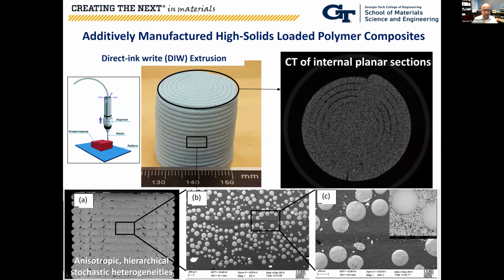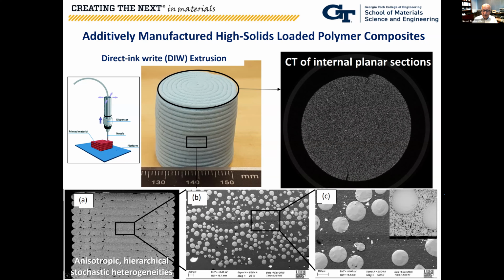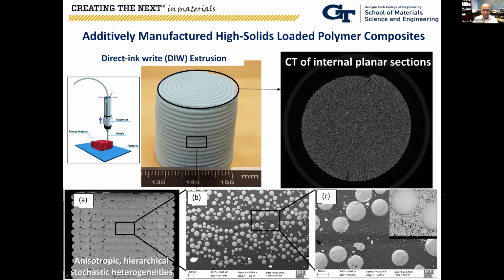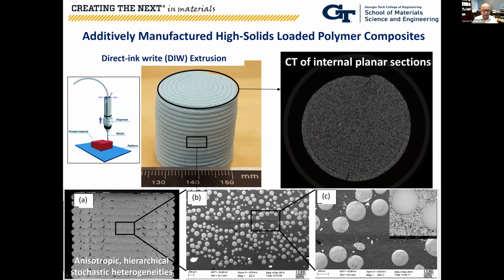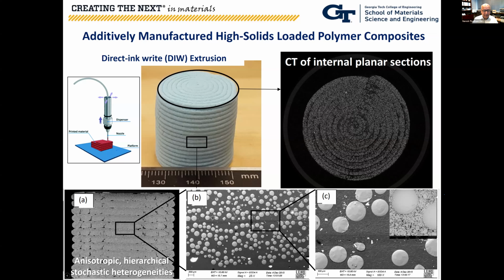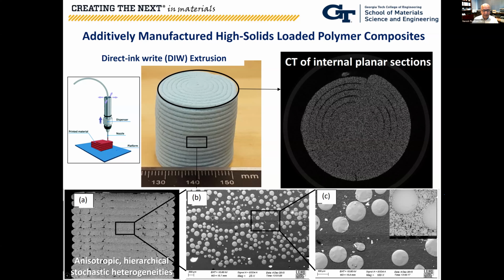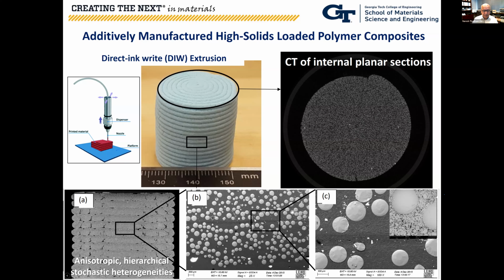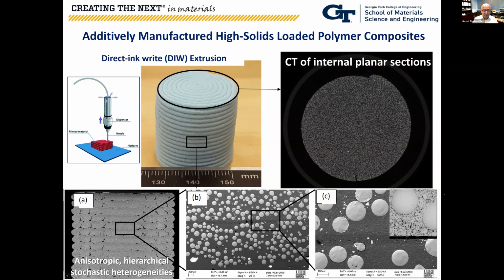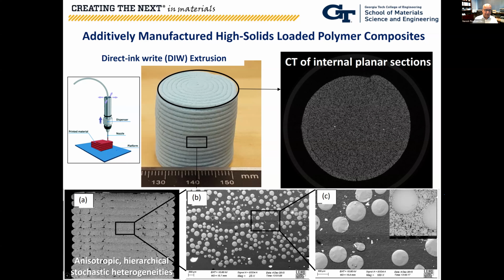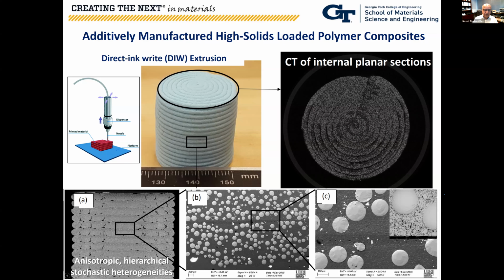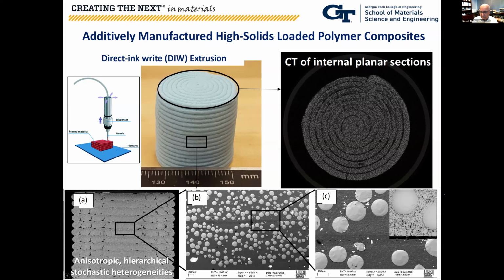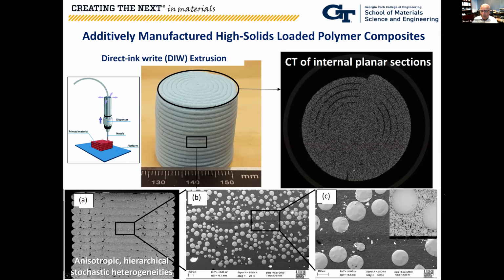And then if you consider the distribution of the particles, again very, very non-uniform. This band that you are seeing is the interlayer, the space between the two layers, and you can see there are no particles in that region. So those are regions that are depleted of particles, and you can see that even better here.